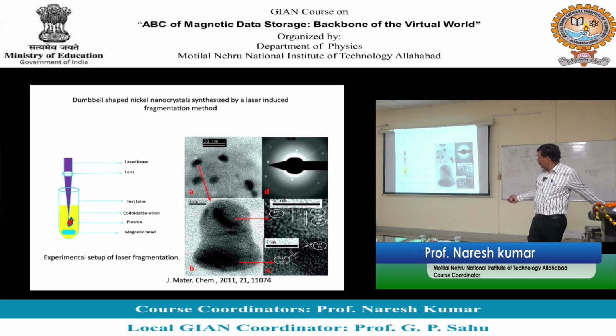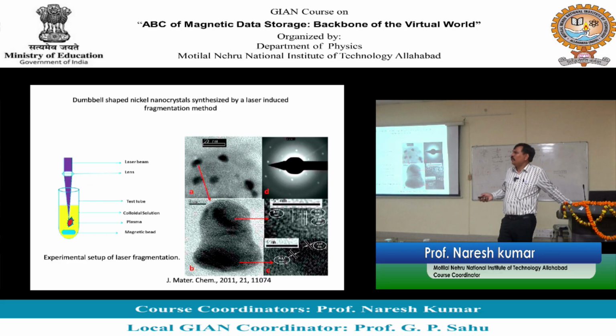It can also be used to grow nanoparticles. Here is a picture. Here you take a material, let's say nickel. If you want to make nanoparticles of nickel, you take nickel, have light coming to it, and it is dipped in some liquid. What will happen? The plasma will be created, and the nanoparticles will be dispersed in the liquid. You can filter it out later. Usually people use acetone, and you take the acetone on something. After some time, the acetone will evaporate, and you will have nanoparticles left.